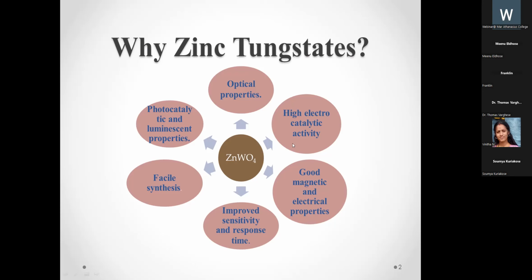In addition to that, to enhance the property of zinc tungstate, different strategies such as modulating crystallinity, tuning morphology, and ion doping, etc., have been done so far. Here I have modified the zinc tungstate by using reduced graphene oxide, and by adding reduced graphene oxide to this material, it will increase the surface area and thereby result in more active sites in the electrocatalyst.